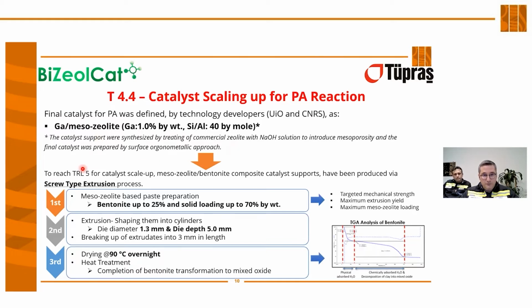To reach TRL 5 level, we used the same approach, but a bit different, because we used bentonite, and we changed the bentonite ratio and solid loading in this composition in order to increase mechanical strength, reach maximum yield and maximum mesozeolite loading to improve catalytic activity.